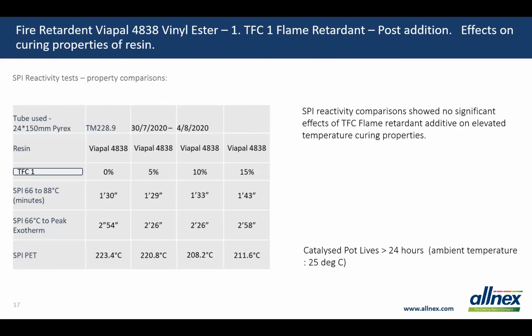Okay, so as far as the fire retardant blends that we've been playing with on 4838, I mentioned earlier that sometimes these types of additives can affect other properties of the resin, including the reactivity or the line curing properties. And we look at SPI reactivity tests, a basic characterization, to see if increasing levels of this additive actually cause any inhibition. This is just a common laboratory method.